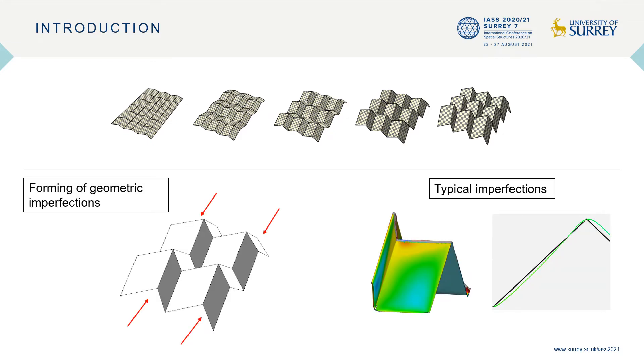To manufacture these cores, they are folded by applying external forces at specific points to basically push the structure up. As a result, depending on the geometry, the fold cores can deviate from the originally intended design, which has flat face sheets and straight crease lines. Instead, geometric imperfections can form that show bended face sheets or rounded crease lines, like you can see on the right.